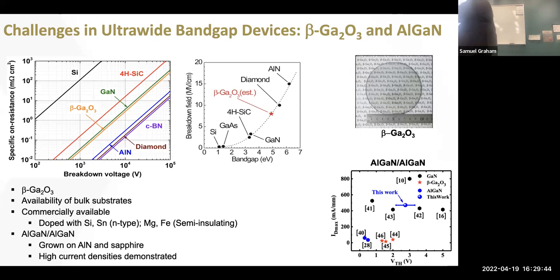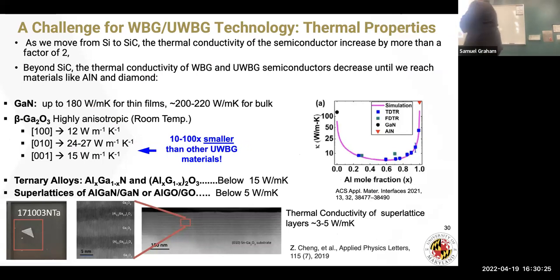RF devices. What's really nice about beta gallium oxide is that I told you before that those 2-inch gallium nitride wafers are commercially hard to find. Well, since this is an oxide, people can grow this to very large diameters. So the commercial availability is there. But again, the issue is that this material has a very low thermal conductivity. People have made devices like these transistors that actually rival some work that you've seen in gallium nitride. So this is actually good work being done in terms of current densities. And you'll see some other work coming out in terms of beta gallium oxide as well, that's starting to show some promise. So let's start looking at the issues here.